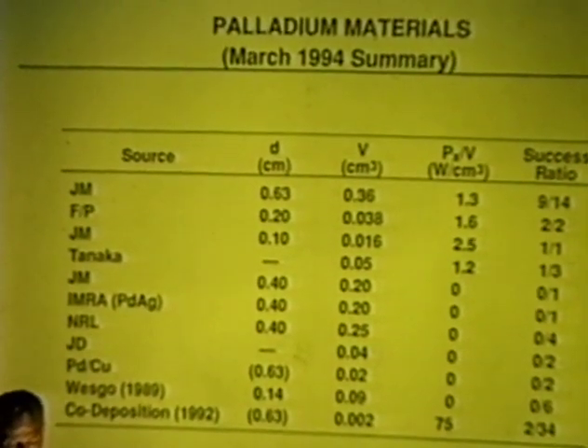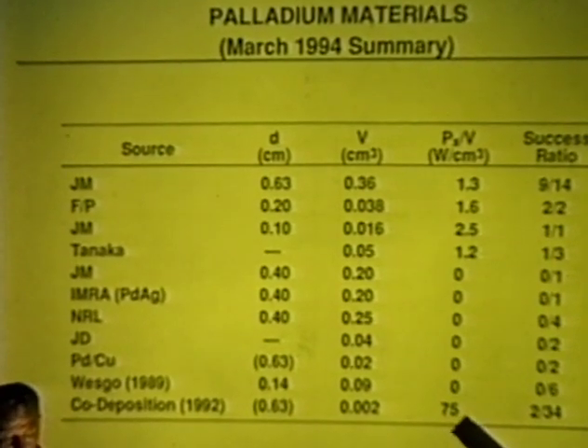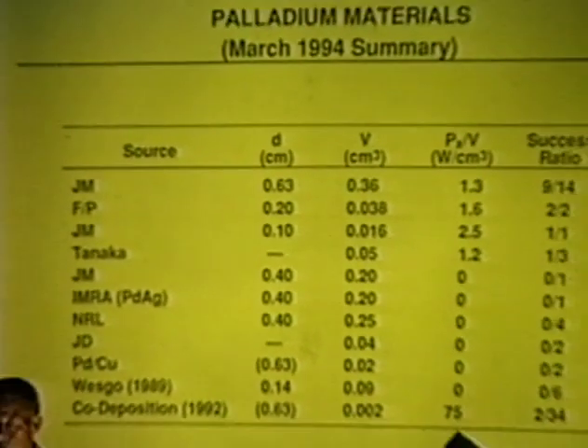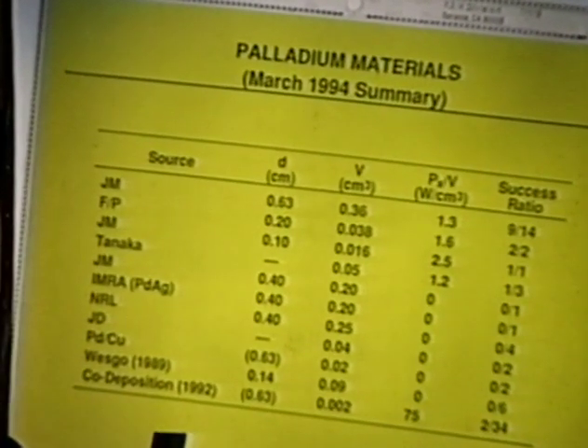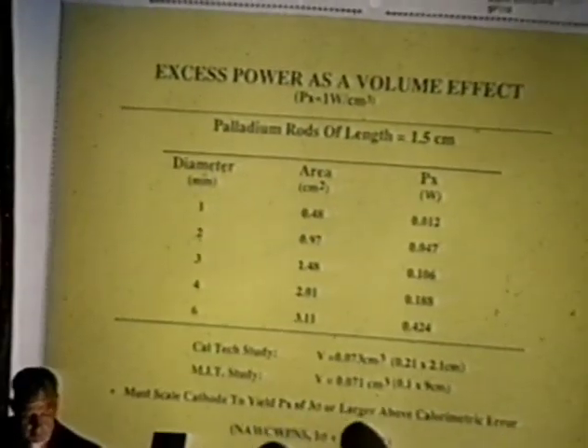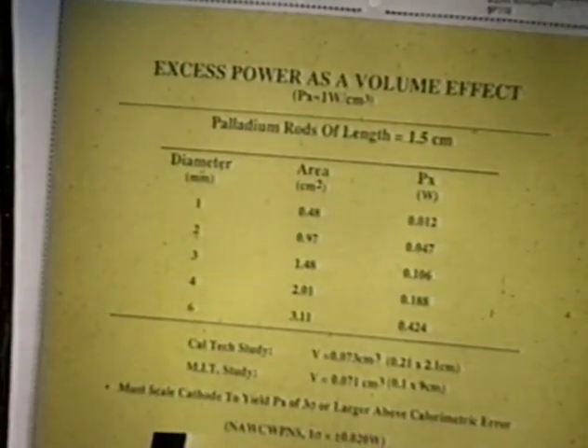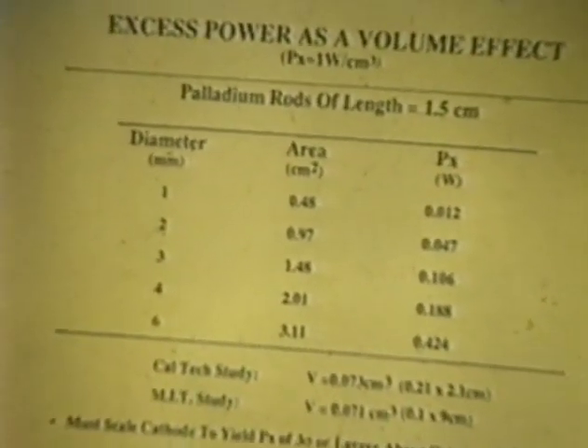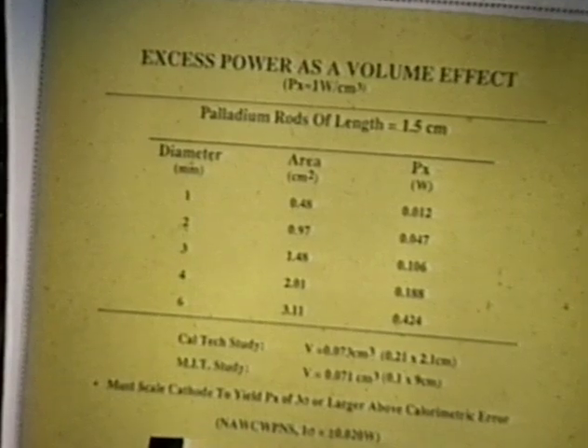Recombination, and to explain those results, we would have to have had a high power density, 75 watts per cubic centimeter, to measure the small excess heat that we saw. And that points out that the effect seems to be a volume effect as far as we could tell. We're not sure. It could be a surface effect, but I roughly figure you get about 1 watt per cubic centimeter of palladium. And that gives you an idea of what to expect for your experiments.